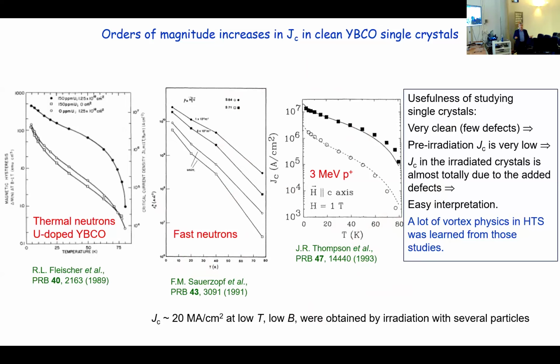So why was it useful to study single crystals? Well, first of all, because they are very clean. So they have very few defects to start with. The pre-irradiation JC is very low. So when you irradiate, anything that you see in JC is coming from what you put there controllably. So the interpretation is much easier.